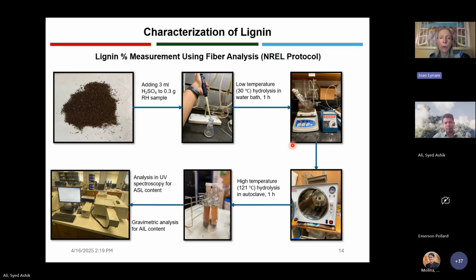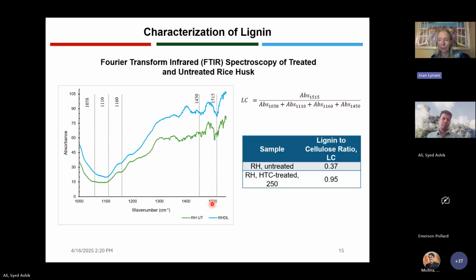We then put it into a 30°C hydrolysis bath for 1 hour. We then autoclave it at 121 degrees C for 1 hour. We then weigh how much solid we have. The solid that we get is called acid insoluble lignin, AIL, because we put it in the acid and it did not dissolve. Finally, we take the liquid that was there and analyze it with UV spectroscopy for acid soluble lignin, the stuff that dissolved out. So that's how we are characterizing our lignin.